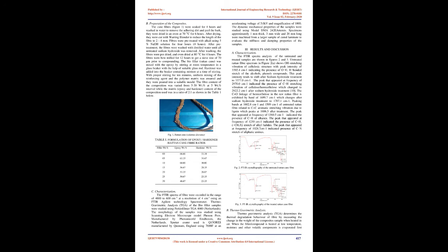The biofiller, rattan cane, was mixed with the epoxy by stirring at room temperature in a glass beaker with the help of a suitable glass rod. Hardener was added into the beaker containing the mixture while stirring. With proper stirring for 10 minutes, uniform mixing of the reinforcing agent and the polymer matrix was ensured, and they were poured into a suitable mold.